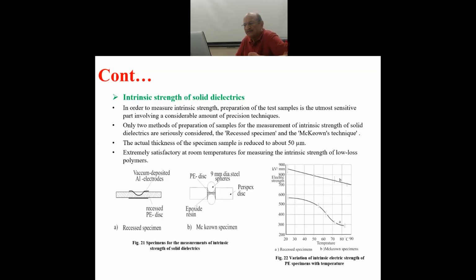If you might have read in some literature that the breakdown strength of this solid material is this much, people don't specify under what conditions it has been measured and what type of breakdown strength is being conveyed. So in fact, to talk about the breakdown strength of solid dielectrics, unless you know under what conditions it has been done, it could be misleading. The values measured could be of this order, if you have taken care. Simple polyethylene to the tune of 850 kV per millimeter is unbelievable for some. So misleading figures are available in the literature.